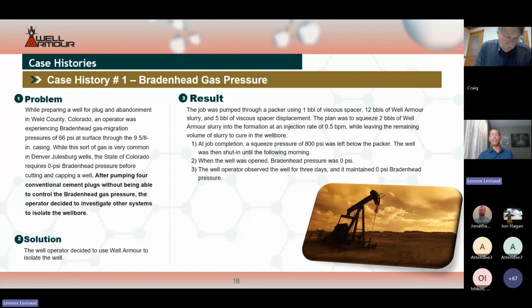Here's a case history example for which Well Armour was used in the DJ Basin, Colorado, during a plug and abandonment operation. The well operator was experiencing 66 psi of Braden head gas pressure through the 9 5/8-inch casing. After pumping 4 conventional cement plugs unsuccessfully, the well operator decided to use Well Armour. Squeezing through a packer at 0.5 barrels per minute, 12 barrels of Well Armour slurry was pumped, of which 2 barrels was squeezed into the formation, and 10 barrels of the slurry was left in the 9 5/8-inch casing. A squeeze pressure of 800 psi was left on the Well Armour slurry overnight, and when the well was opened up the following morning, the Braden head pressure was 0 psi.